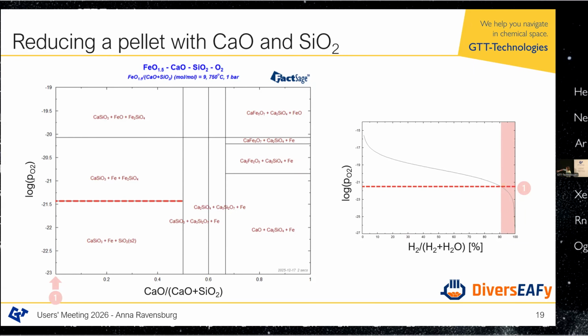But if we look at this now, and go further to the right in this diagram, then actually the full 100% conversion of iron moves up. It moves up to minus 20.1 if I add more CaO. And if I look at the plots with the oxygen partial pressure, this also means that the region of how much H2O vapor I can have in my furnace moves to the left. So I have a much bigger process window for my furnace in order to actually reach the 100% conversion. Again, without this, I could only reach 87%. That's not enough for most of the processes. So it's quite relevant where I am in this phase diagram and what this ratio of SiO2 to CaO is.